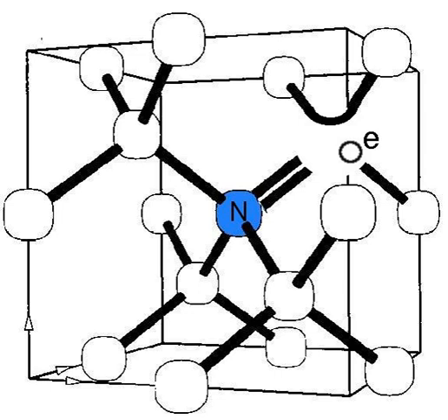Topic: Production. Nitrogen vacancy centers are typically produced from single substitutional nitrogen centers, called C or P1 centers in diamond literature, by irradiation followed by annealing at temperatures above 700 degrees Celsius. A wide range of high-energy particles are suitable for such irradiation, including electrons, protons, neutrons, ions, and gamma photons.